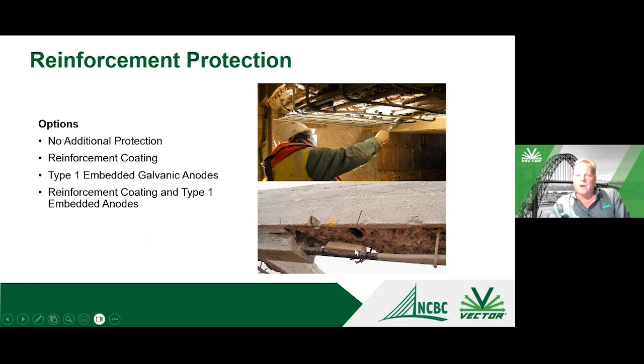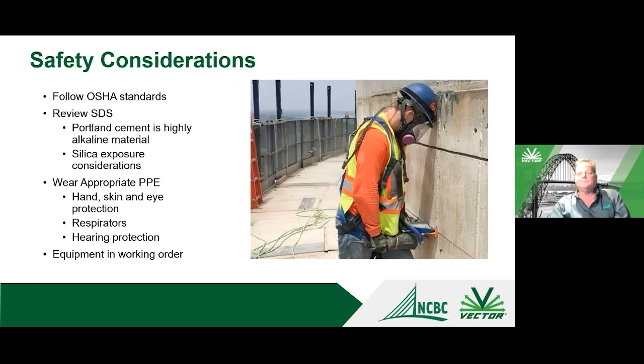This picture on the bottom right is a picture of an embedded galvanic anode that's connected to the reinforcing steel, which is going to provide protection to that bar. And then also you can use the embedded galvanic anodes in conjunction with the reinforcing coating. There's some synergy there, where you provide protection to the steel in the repair through the coating, but the anode is providing protection to the surrounding concrete. And we'll talk a little bit more about that in a second.